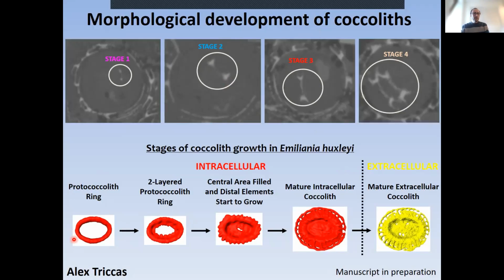We have the formation of this proto-coccolith ring, as it is called. It's a ring of rhombohedral crystals of calcite. We don't have the resolution here to resolve the crystals, so that's why it looks like a continuous ring. In the next stage, we see that the proto-coccolith is larger and taller, what we call a 2-layered structure. It's taller, and then we start to see growth towards the inner part and the start of development of those struts of the coccoliths. Then we get mature coccoliths, still intracellular, but they already have the mature morphology, and then you have the extracellular ones that are here in yellow.